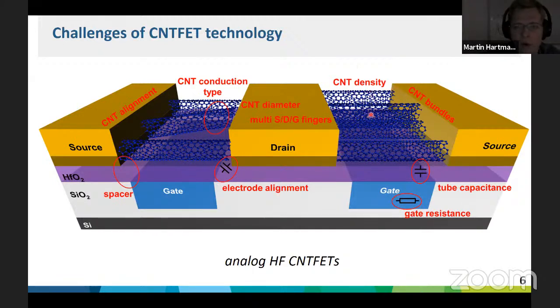Okay, so ideally you have a really high CNT density, with a spacing of about 5 nanometers, so that the interaction between the CNTs is not so strong, but you have a lot of them integrated, so you can reduce the size of your device, and this further reduces parasitic capacitances. So all in all, there are a lot of aspects that you need to cover.